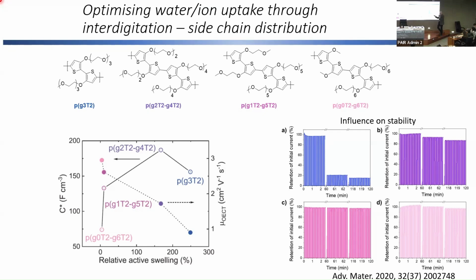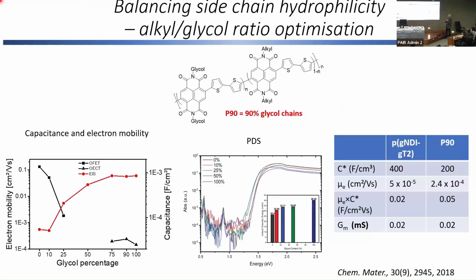But one interesting thing that came out of this work is that when you have a low degree of ordering and a high degree of irregularity, low density, then when you start to repeat your transistor cycles, you see a big drop in the current. So the stability of these materials seems to be, to a large extent, inversely proportional to the water uptake. So we want to try to reduce that.